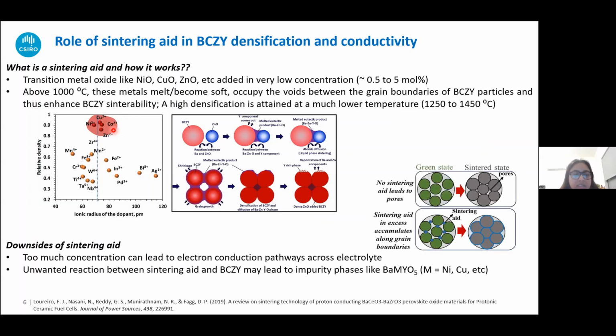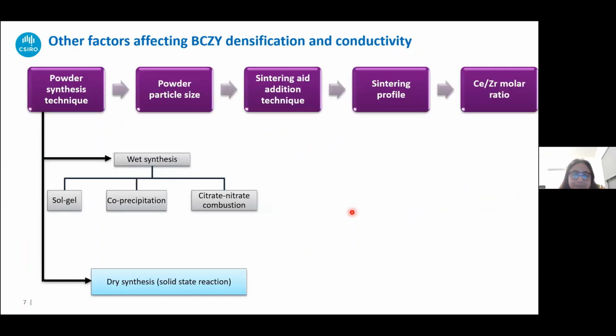However, there are certain downsides. If these materials are added in too much quantity, since these are metal oxides, in a reducing atmosphere they get reduced into metals, and in high concentration they can lead to electron conduction pathways, and that is not something which is quite favorable. And also, these can react with the BCZY and produce unwanted phases, which can act as impurity phases, and that also leads to a drop in the ionic conductivity.